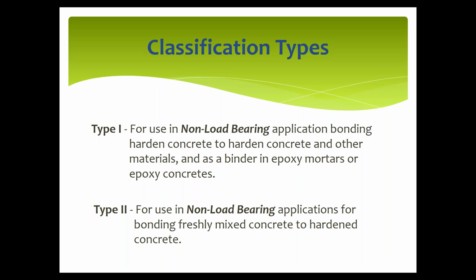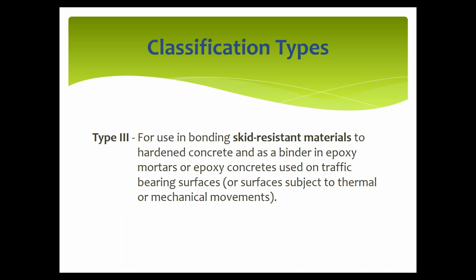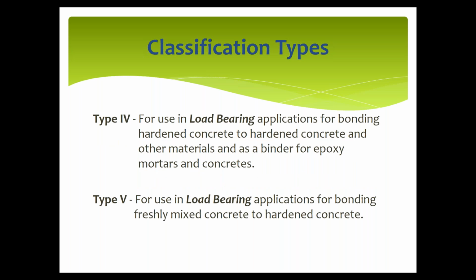For the classification type, you have Type 1, which is used in non-load bearing application for bonding hardened concrete to hardened concrete and other material, and as a binder for epoxy mortar and epoxy concrete. Type 2 is used in non-load bearing application for bonding freshly mixed concrete to hardened concrete. Type 3 is for bonding skid resistant material to hardened concrete and as a binder in epoxy mortar or epoxy concrete used on traffic bearing surfaces subject to thermal or mechanical movement. Type 4 is used in load bearing application for bonding hardened concrete to hardened concrete and other material, as a binder for epoxy mortar and concrete.